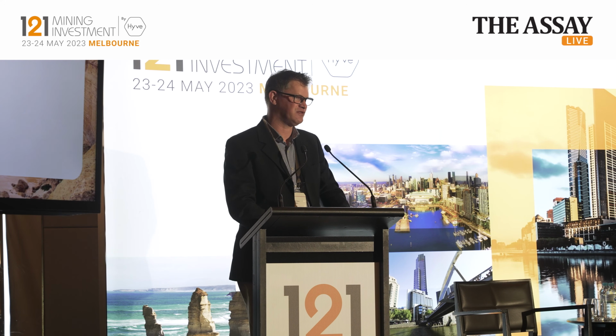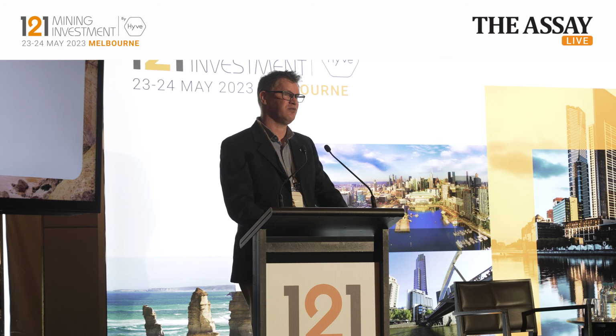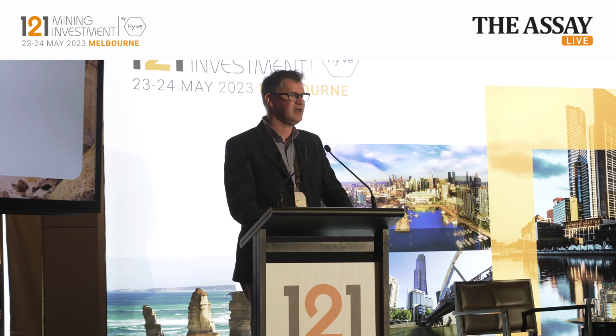So most suppliers such as BTR, Showa and others are selling you an artificial material in most instances. It's a very stable material, so it's well characterized and it doesn't have some of the well-known degradation mechanisms that natural graphite has, one of which is a swelling issue. So with time, the particles will expand and contract, and you'll lose electrical contact in the material, and also you have some additional SEI challenges. Some of that can be dealt with through the processing mechanisms, through the carbon coating, and also some electrolyte additives.